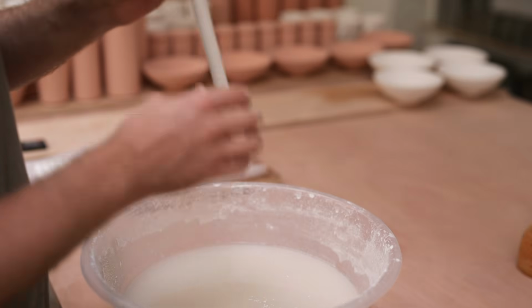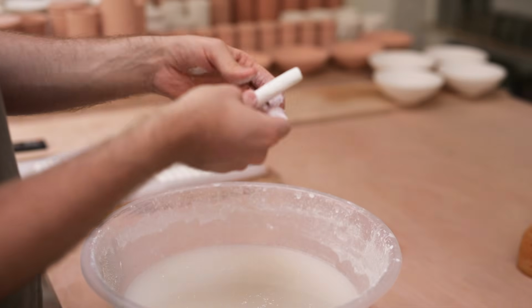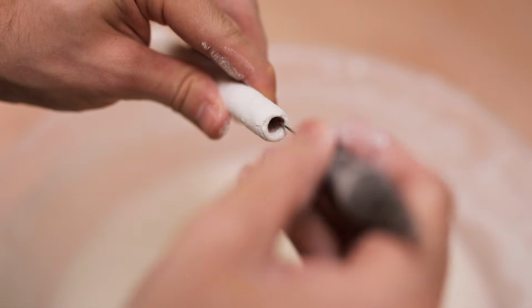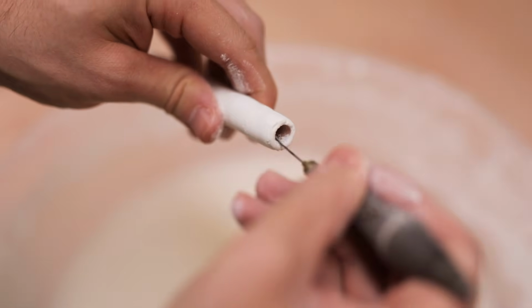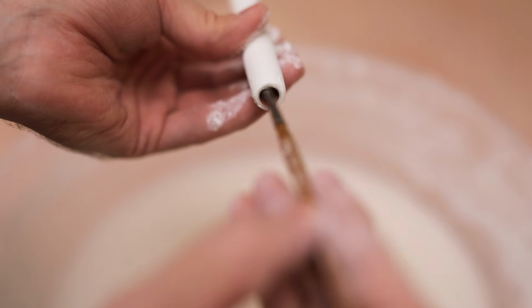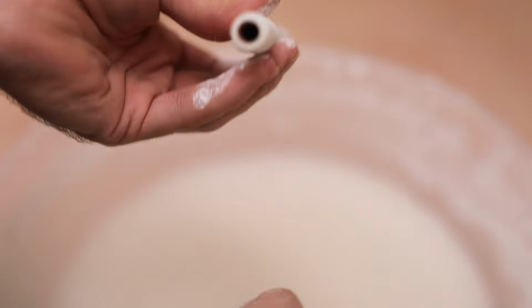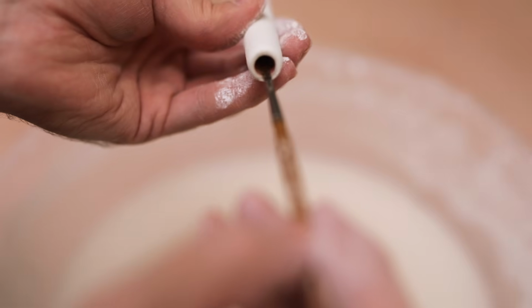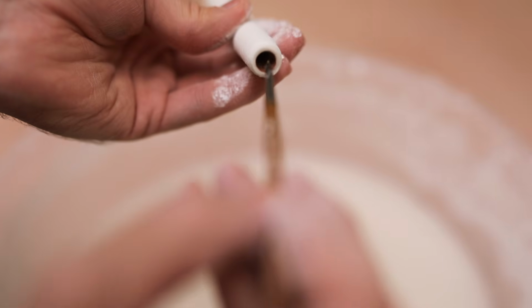So once I've fettled clean the outside surface of the pen, I used a potter's needle just to scrape away a bit more of the excess glaze, before switching to a paintbrush and simply doing what I did before. The white glaze is particularly delicate and is far more powdery and fragile than the red glazes, so I do need to be more gentle as I carefully brush away this small ring of glaze.